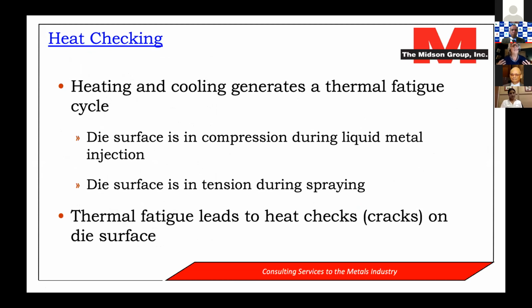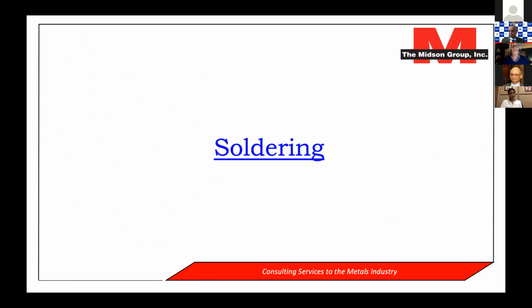What this means is that we get this thermal fatigue cycle every time we make a casting. When we inject the liquid metal, the die surface is in compression. When we spray, the die surface is in tension. So this tension, compression, tension, compression gives us a fatigue cycle, and this thermal fatigue leads to heat checking, or cracks on the die surface. Then if we go on and talk about soldering.